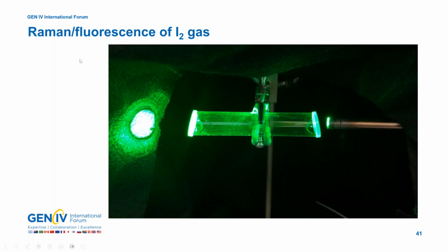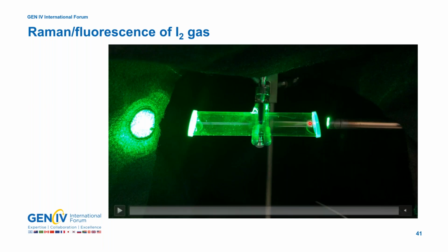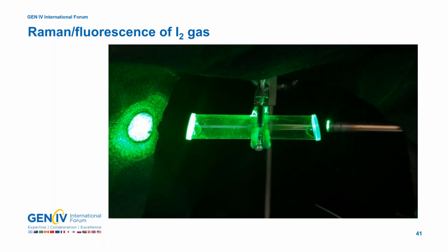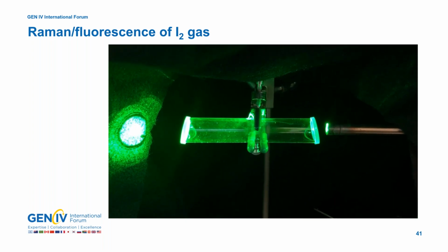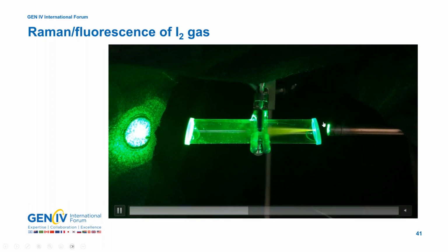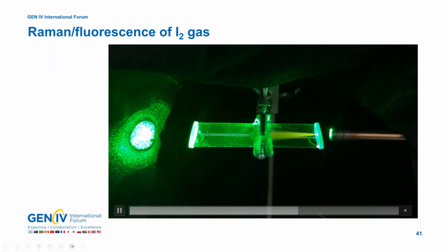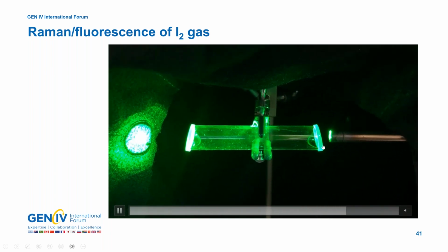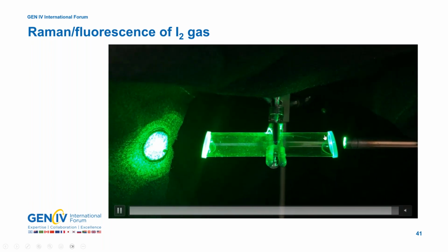The first slide I want to show is the measurement of I2 with one of our gas sensors. This is I2 gas, and just to set this up, this is a gas tube filled with iodine gas. This is our Raman probe that we put adjacent to our gas cell, using a 532 nanometer excitation beam, and we were intending to measure the Raman spectrum, which we did. But also, this is a video. We can see that we get really nice fluorescence being generated, and it's pulsating actually, which is pretty interesting.